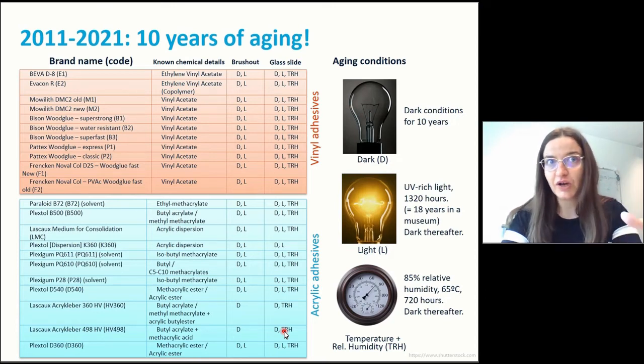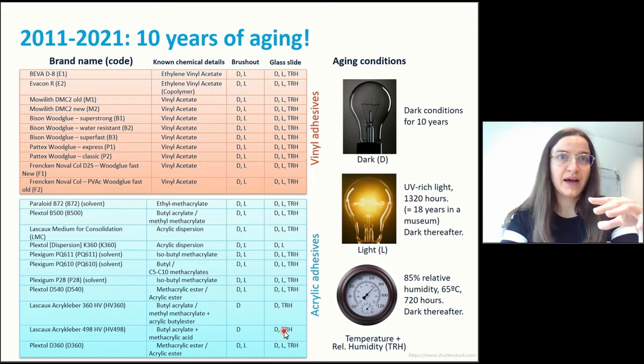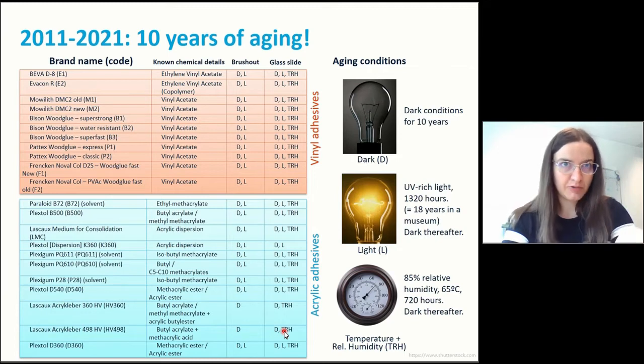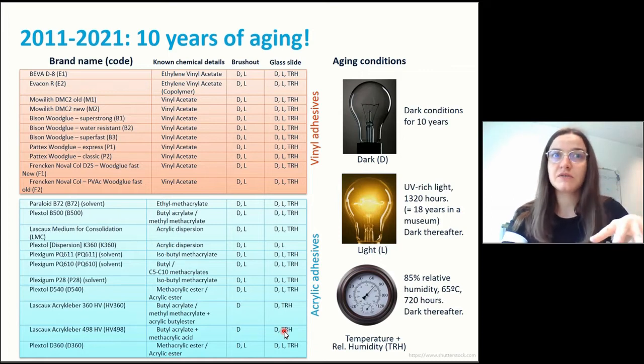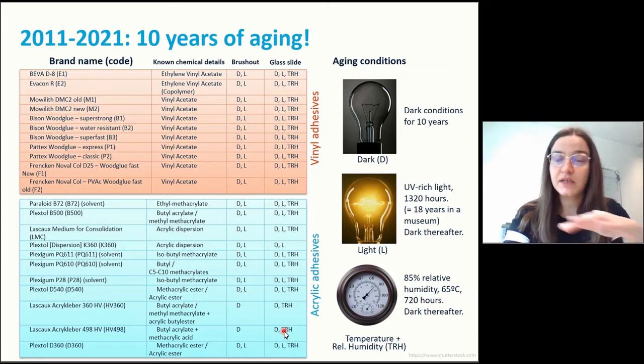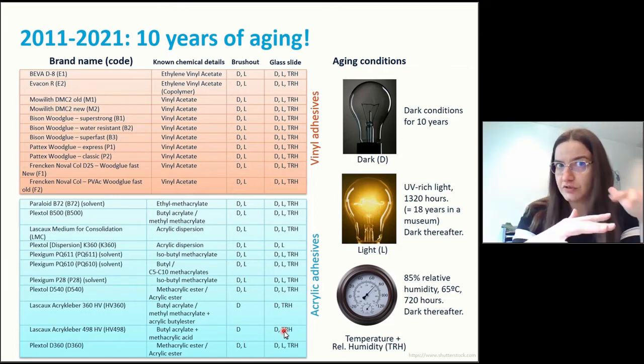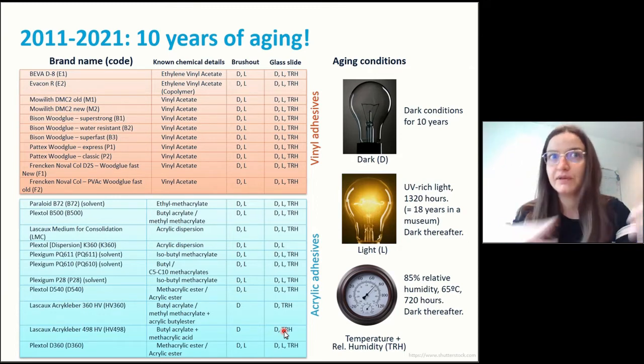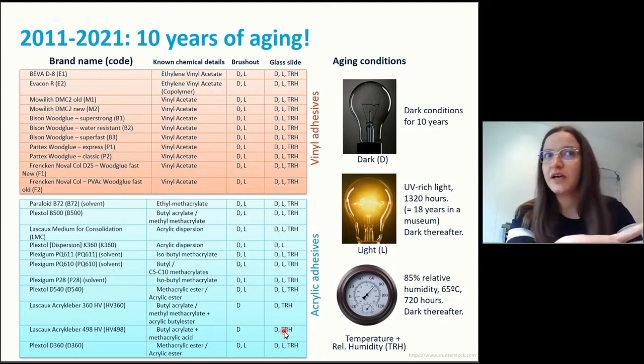So they were put in a light chamber with UV rich light for 1,320 hours. When you do the conversion with the flux of light that this has been exposed to, this is equivalent to an object that has been 18 years in a museum with a standard lighting of a museum. After this treatment, the samples were moved and kept in the dark for the rest of the period. So we will assume that most of the variation happened during the light aging. Everything else is following natural aging.